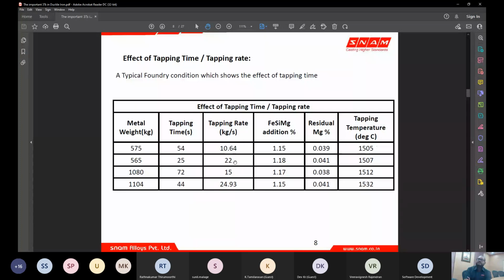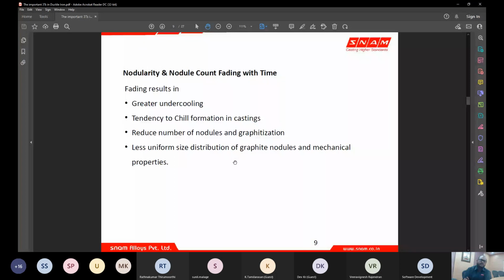And we know very well that nodularity and nodule count fade with time. Nodularity is to some extent decided, or very much dependent, on the residual magnesium, the section sensitivity and the section thickness of the casting, and cooling rate also. As all these things are related over time, time plays a major role. So there is a specific time available, and control over time is to be maintained.